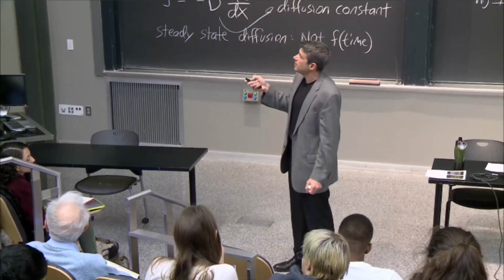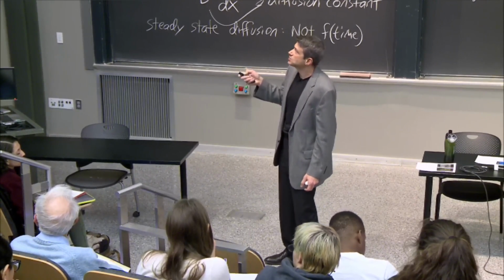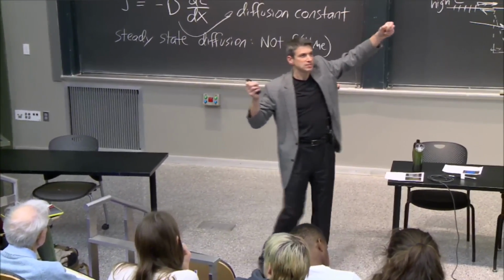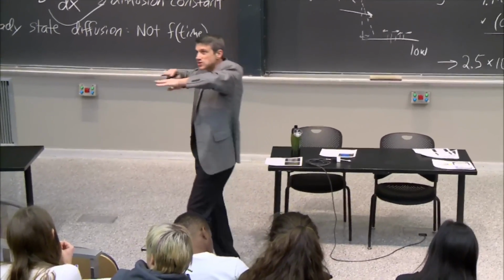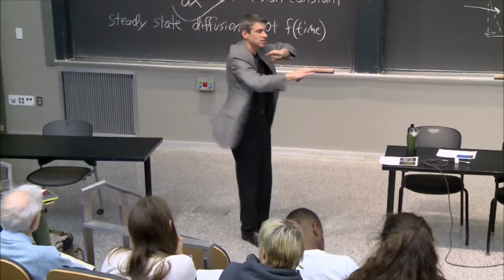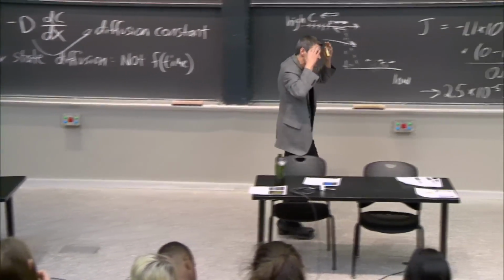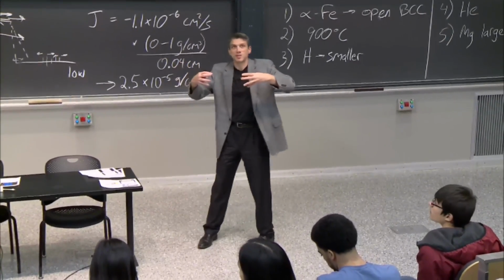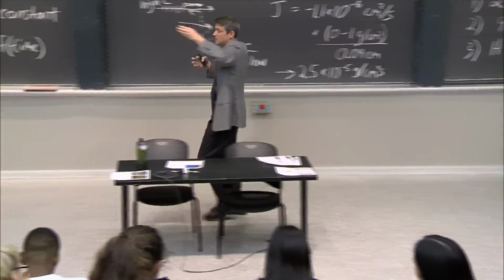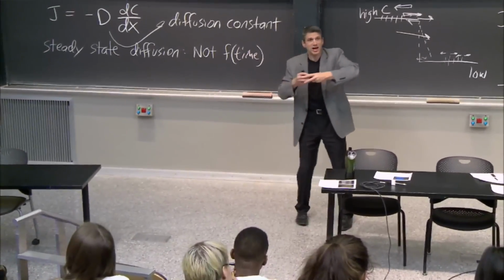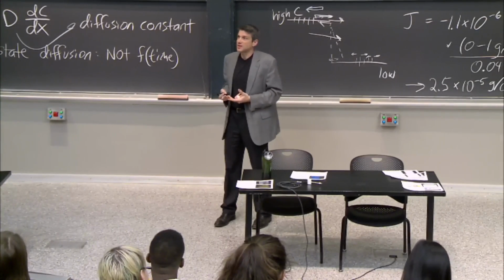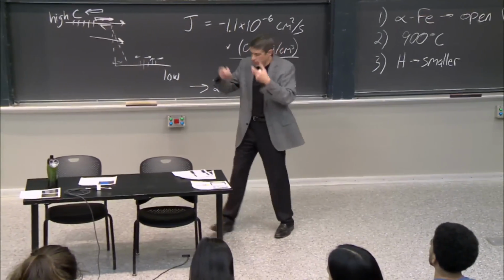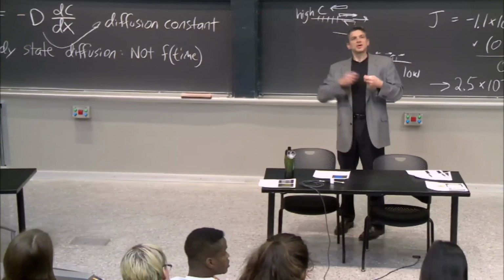But then you say, well, maybe I need 3D voids. Maybe it shouldn't have channels. It should have voids so it can choose more paths, okay? Or maybe we have planes. Maybe it's a layered structure where they have these 2D planes they can travel through. What's the best? Well, it's not trivial because it's one of these, as usual, constrained optimization problems where when you make the pathway faster, you might need to have more voids where you'll lose material. Or maybe you make the material unstable, right? So you're kind of fighting, you want it to have a really high density, but you also want it to...